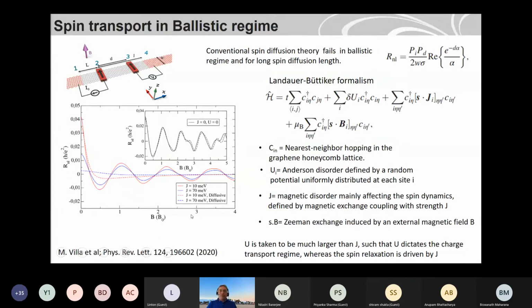Yeah, so there was an interesting question in the last talk. What about high mobility spin transport? Meaning when spin is not in the diffusive regime, but in the ballistic regime. For graphene, it's a very usual question when you have a good quality graphene where it's not quite ballistic, but it can be quasi-ballistic so that you don't have to use the diffusive equation. This was the diffusive equation: the resistance you see in the spin transport and how it depends exponentially on this length and spin diffusion length. And so this will fail in the ballistic regime.